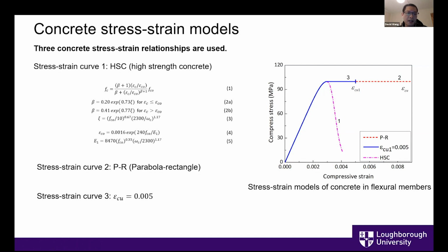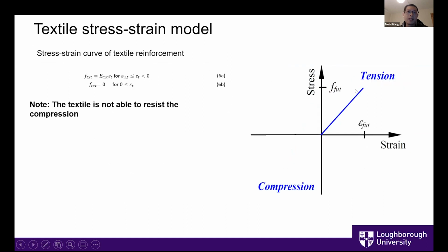The second stress strain curve is mostly suggested by the FIB code. After the ultimate concrete stress is reached, the concrete will be able to maintain this stress until the ultimate axial strain is reached. For stress strain curve 2, we assume the ultimate axial strain will be 0.01. For stress strain curve 3, we assume this ultimate axial strain to be 0.005. For the textile, we assume the textile can only contribute to tension, not compression.